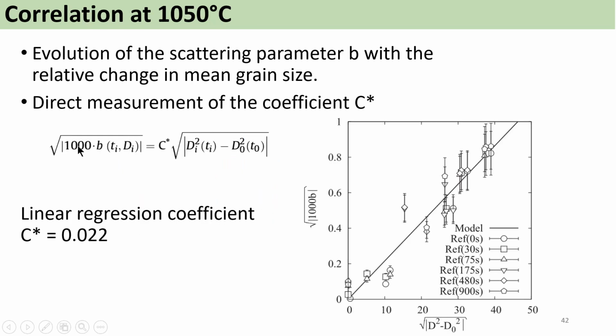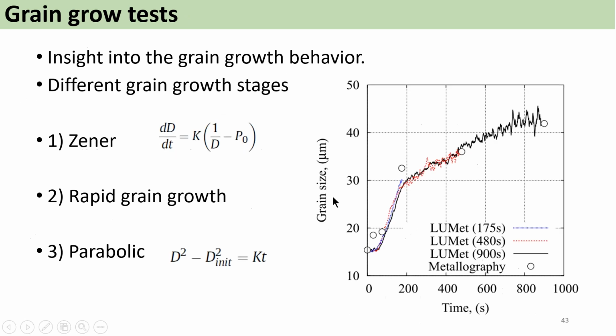We've built a calibration, as was done with austenite in steel. We've done it the same way: a calibration between the grain size measured by metallography and the B parameter measured using Lumet. And then we've measured the grain size. Here we have the grain size measured using Lumet with respect to time, and the dots are measured by metallography. You can see, first, a good correlation between metallography and Lumet. Second, you can see very good repeatability between the measurements using Lumet.